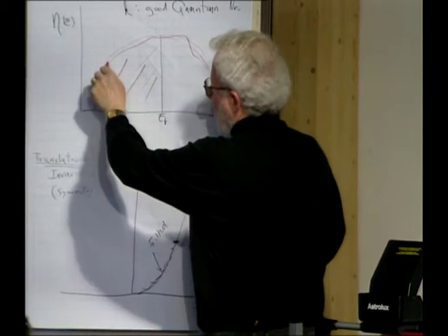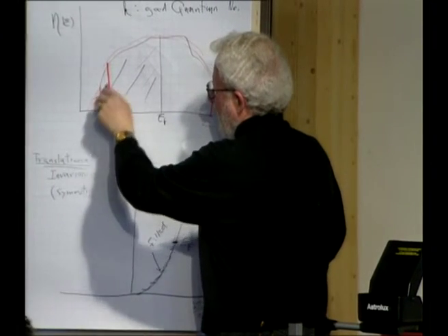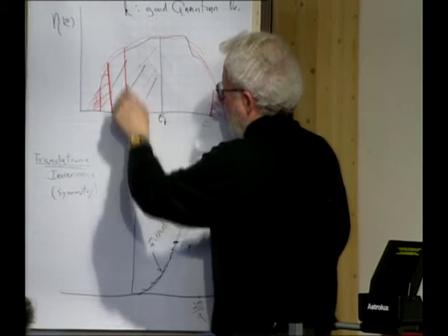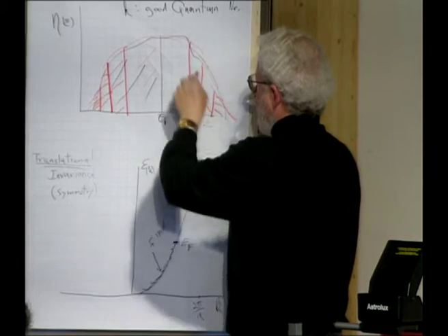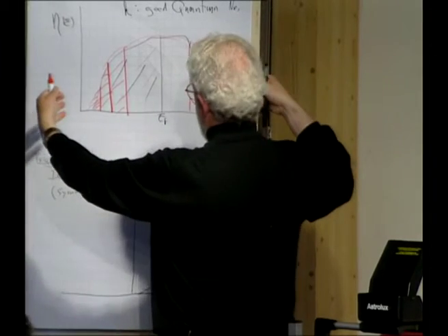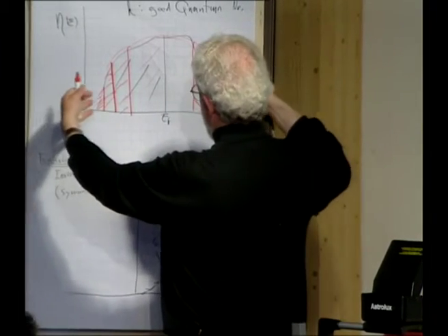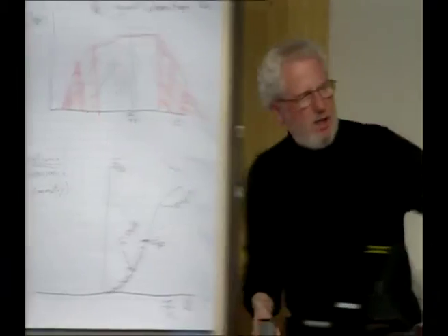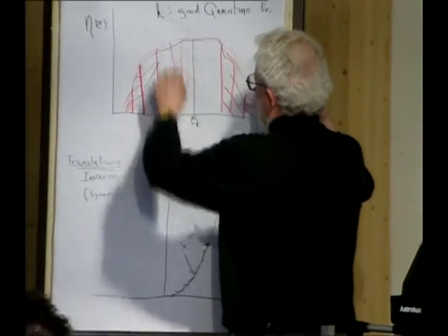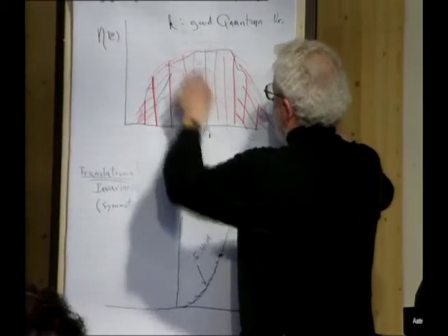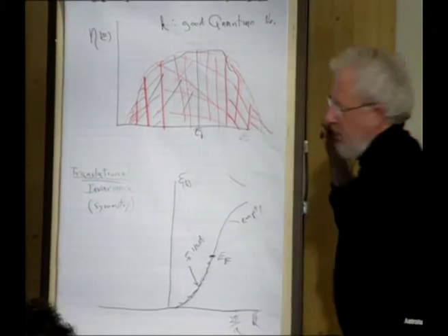If you make the disorder potential bigger, and bigger still, as the disorder increases, states from the band edge, farther and farther into the band, become localized in the sense that I've described here. And in the absolute limit, where the disorder is very large, all those states are localized.